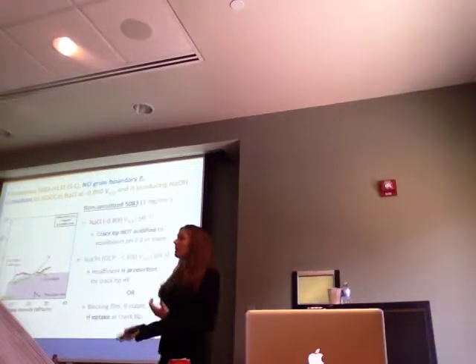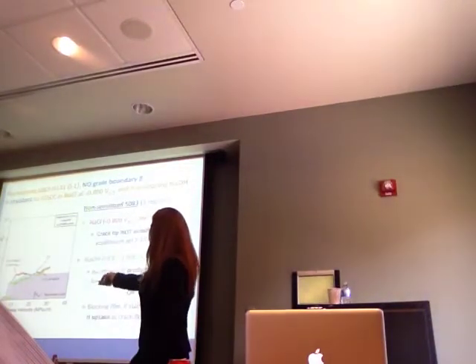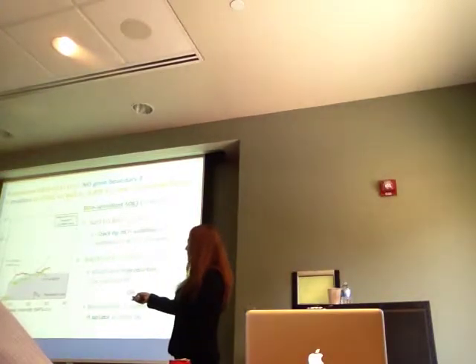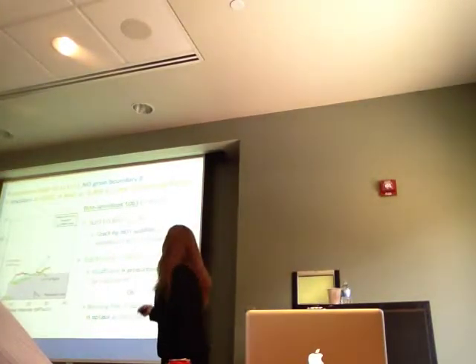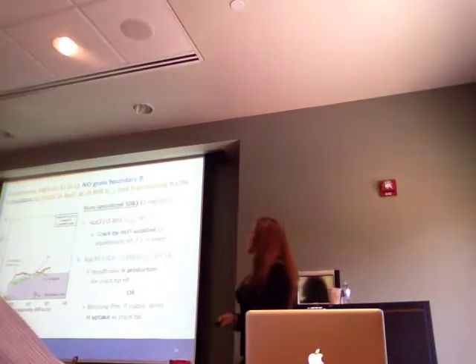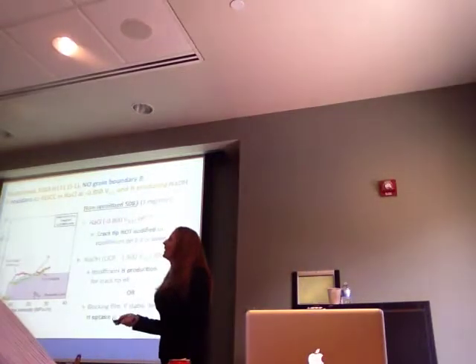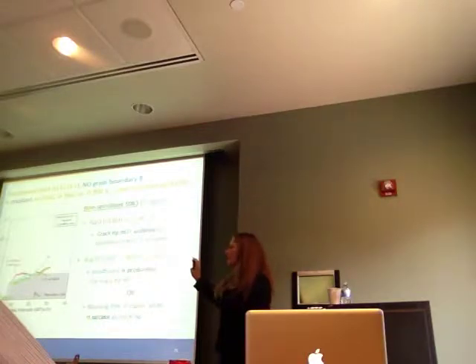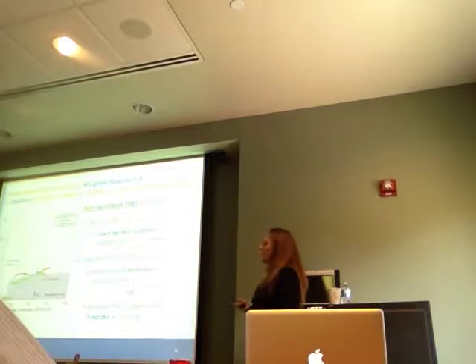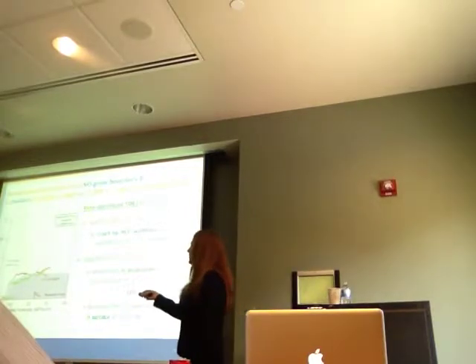So the first thing we need to look at is something I've already shown you. I plotted the crack growth rate here, the stress intensity, and the resolution limit. We're going to focus on this red line here, which is right on the resolution limit. That is the unsensitized 5083 with a mass loss of 3 milligrams per centimeter squared in sodium chloride at negative 0.8 volts. This is the data that I showed you with the threshold stress intensity. So at 3 milligrams per centimeter squared, you're below that threshold. You are resistant to intergranular stress corrosion cracking.